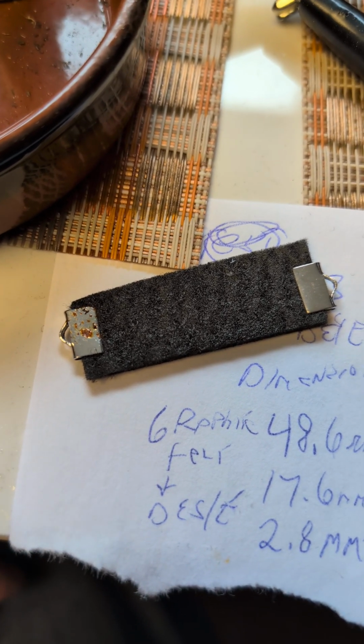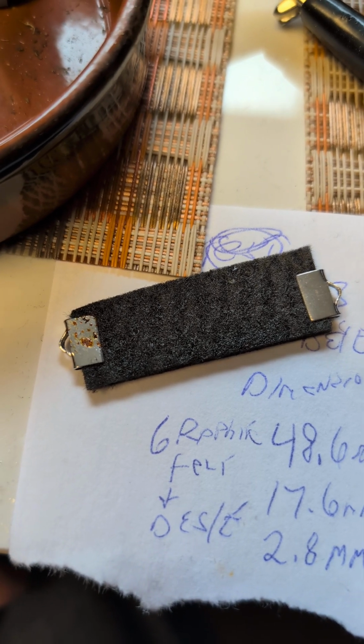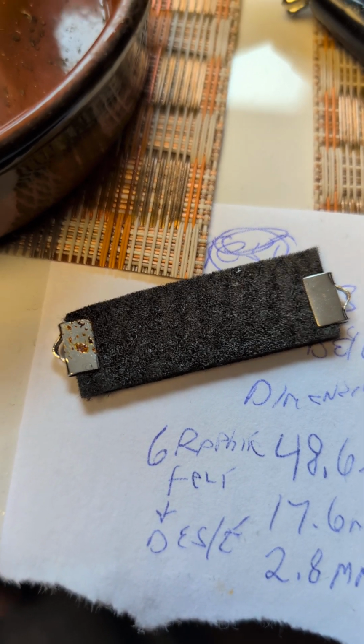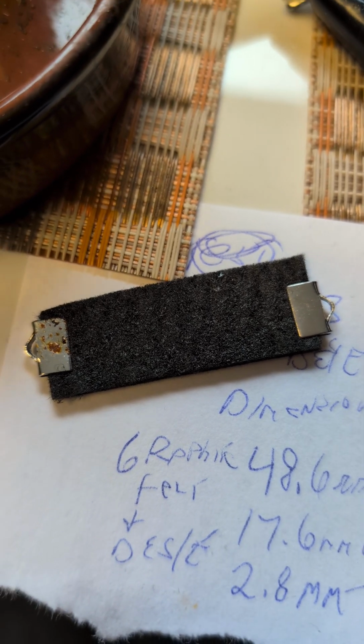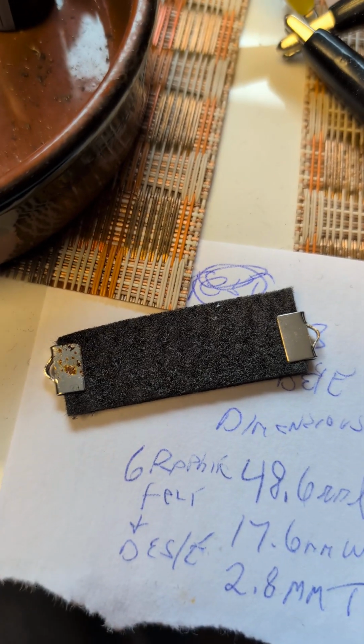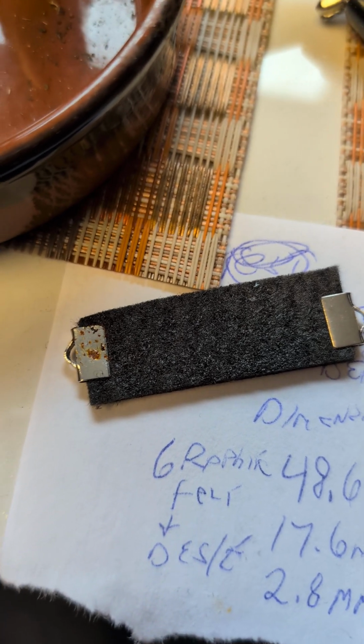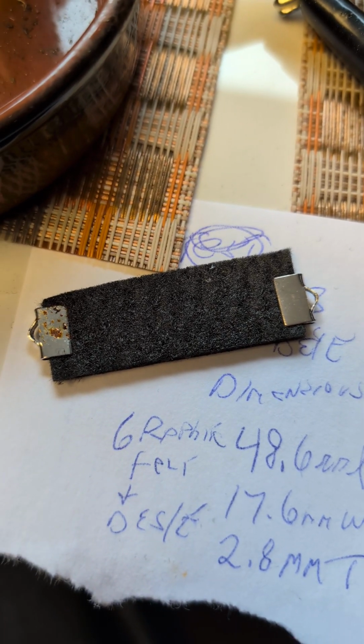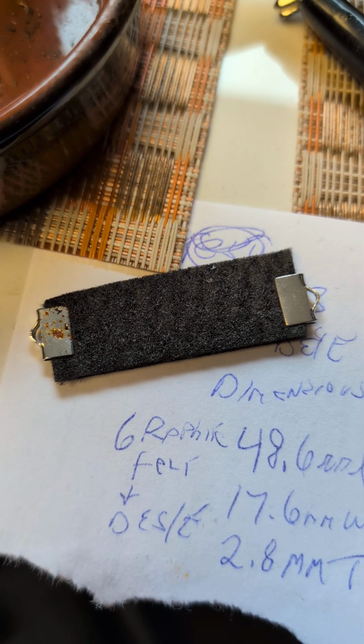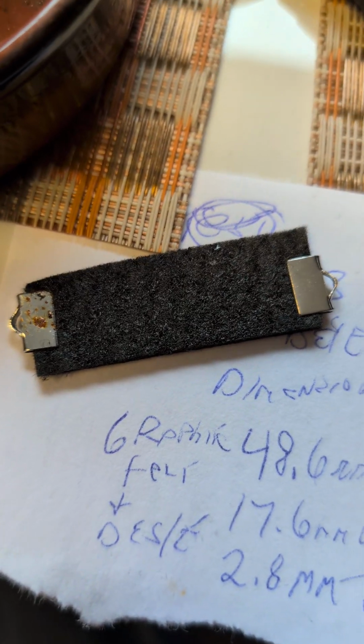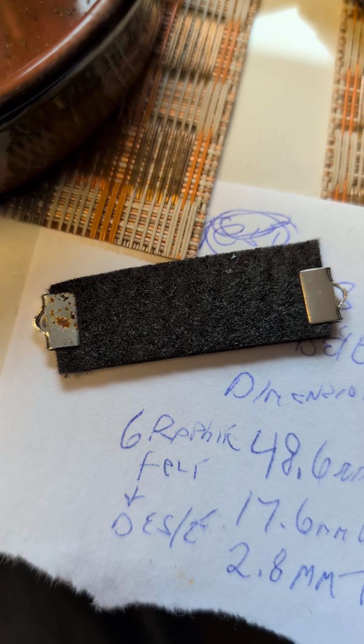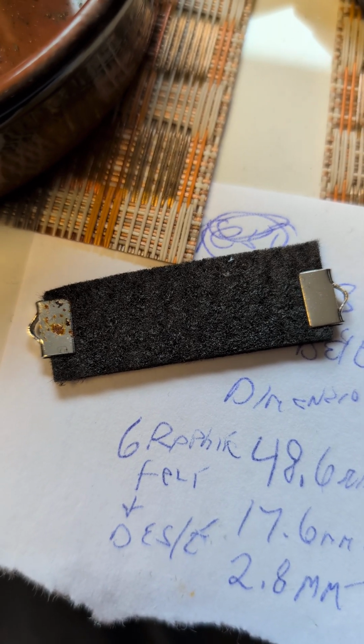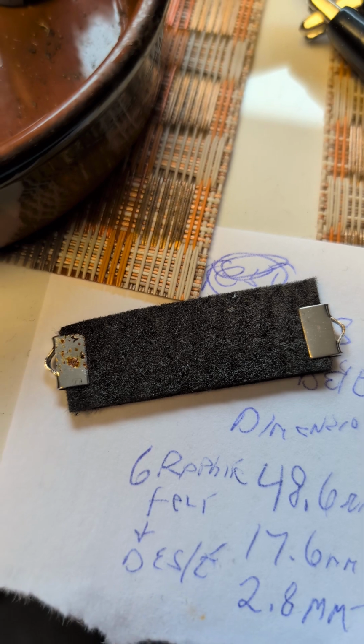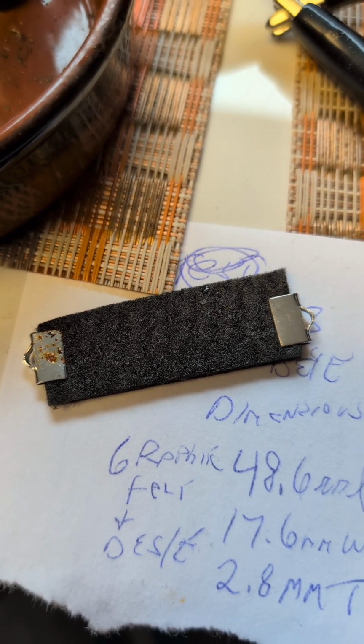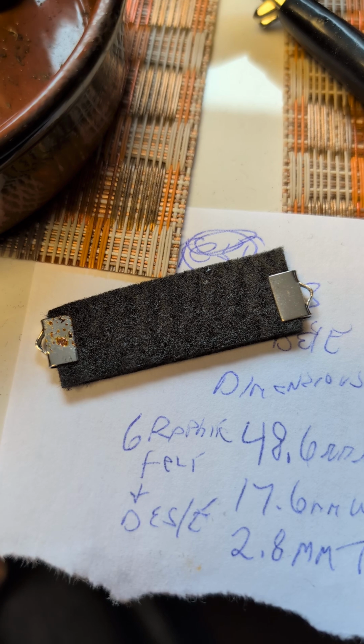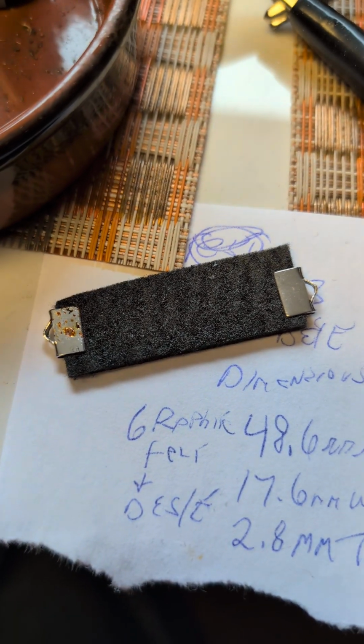It's an excellent introduction, and it doesn't cost a lot of time or money, particularly for undergrads or home researchers, to experiment with different graphite samples. Now, I have graphite yarn. This is graphite felt. And we do nickel plating. We do oxidation of graphite and sonication of graphite. And then we'll continue to get scanning electron microscopic images before and after these power output studies. And then we do cycles of charge-discharge. We've been up to 300 cycles with graphite samples.